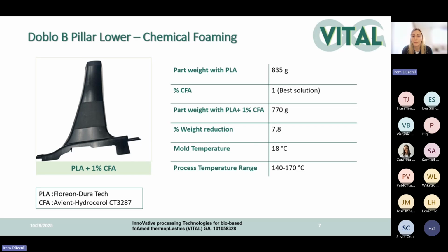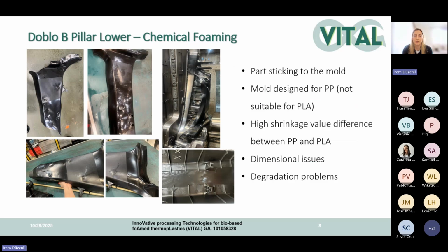You can see that our temperature range is quite a bit lower than for other synthetic polymers, with maximum temperatures of 170 degrees. We also have some unsuccessful parts, which you can see in the pictures. Our most important problem was the parts sticking to the mold. To get rid of these issues, we tried a lot of things, like decreasing the temperature and decreasing the chemical foaming agent. But our mold was made for PP material, and PLA has lower shrinkage than PP, so our part dimensions are quite a bit bigger than the original. This also caused some sticking issues in the mold.